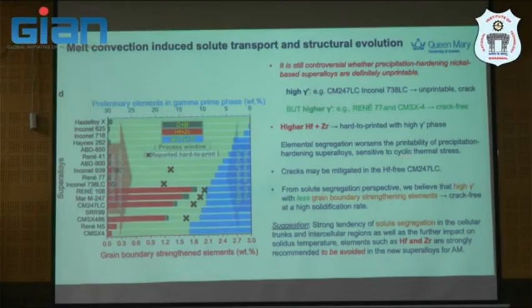Again, we made some suggestion: if we totally remove hafnium, we can print it better. I think you may know some study talking about the variation of hafnium in the CM247 as well. So we believe high gamma prime nickel-based superalloy with less grain boundary strengthening element will be the ideal solution.